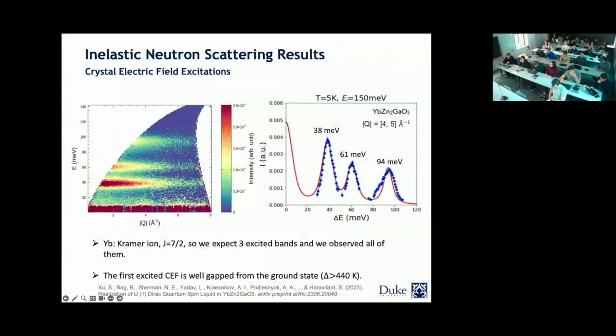Okay, so before I move on to more low temperature stuff, this is the inelastic neutron experiment that we did on a powder compound, just to look at the crystal electric field excitations. Here at 40 meV there's the first excitation, and then you have excitations at around 60 and around 90. Ytterbium is a Kramers ion with J 7/2, so we expect 3 excited bands, and we observed all 3 of them. Given that the first excited state is gapped from the ground state by 40 meV, it's an indication that we have an effective spin one-half for the ground state of ytterbium, if you look at it from single ion physics.